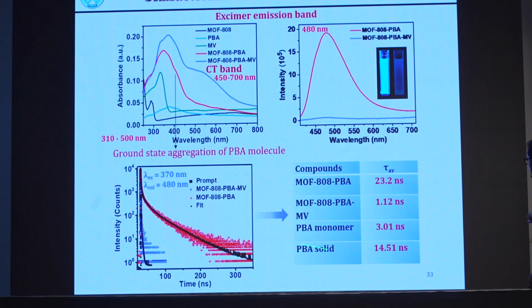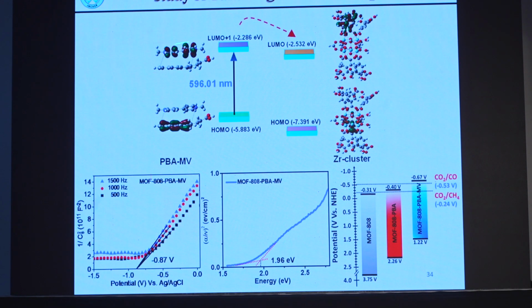So now you can see the lifetime decreases from this, you have this excimer, and with the methyl viologen it is 1.2 nanosecond. There is a charge separated state in normal light, but when you synthesize this molecule in the dark, there is no charge separation. We have done it, okay? So this is the feasibility of the electron transfer: HOMO is in the pyrene butyric acid, LUMO in the methyl viologen, and it can go to the cluster easily.